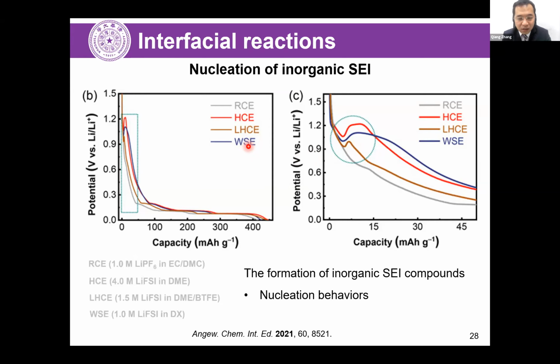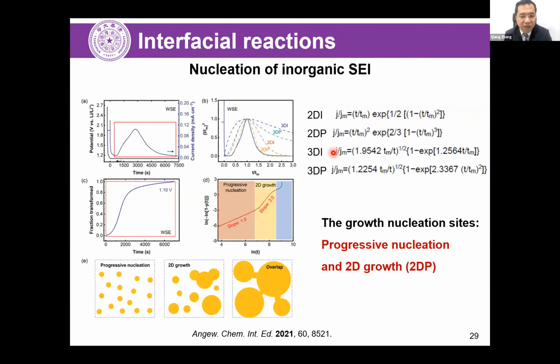Well, the final electrolyte was the weakly solvating electrolyte, which has a very low dielectric constant. The electrostatic interaction will be very strong, and the ions prefer to be coupled in the electrolytes. There is also a wide peak in the surface. So we try to assign this to the decomposition of the solvent and salt for the SEI formation.